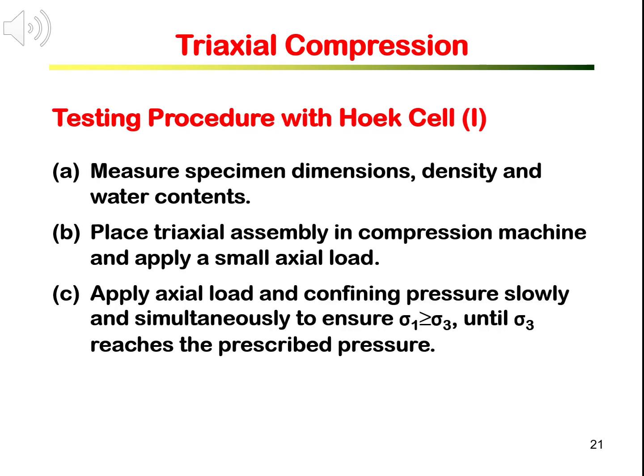The testing procedure described here uses the Hoek cell. First, we need to measure and record the specimen diameter and length a few times at different heights and sides. Then measure the weight and record the water content condition. Attach the axial and lateral strain gauges to the specimen. Place the specimen into the rubber sleeve and the triaxial cell. Attach steel platens to the specimen, then place the triaxial assembly in the compression machine, centered with the axial loading piston. Connect strain gauge wires to the data logger.